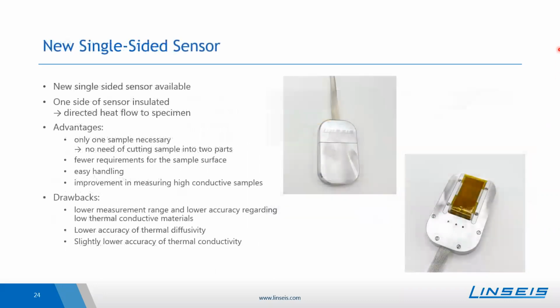What is new since a few weeks is the single-sided sensor. The difference to the other sensors is that you need just one piece of sample. As mentioned before, for these foil sensors you typically need two sample pieces to sandwich the sensor in between. With the single-sided sensor, you can measure just one piece of sample. One side of the sample is covered with insulation material so that one can assume a directed heat flow from the sensor directly to the sample.